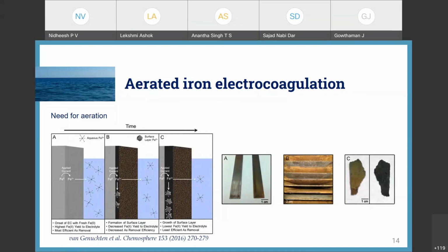They found that magnetite formation is very high. In the initial stages the electrode dissolution is very high, but in later stages it is very low. You can see the magnetite formation over the surface of the electrode. Normally we call this passivation of the electrode, and we can reduce it by mechanical cleaning or by changing the polarity. But in real field implementation, it is sometimes quite difficult to do all these things.